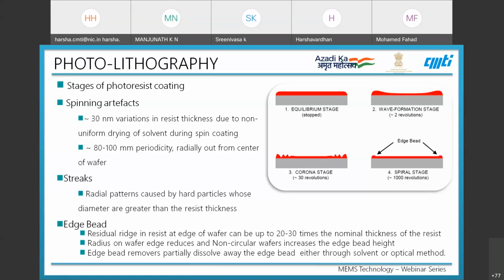So the issues that can arise during the process include spinning artifacts, streaks, and edge bead. Approximately 30 nanometer variations in resist thickness could result from non-uniform drying of solvent during spin coating, and approximately 80 to 100 mm periodicity radially out from the center of the wafer due to spinning artifacts can be observed.